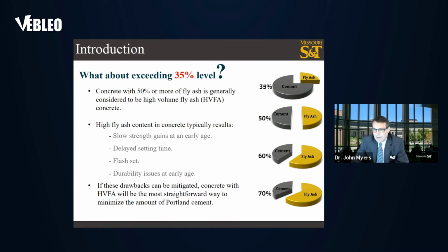So high volume fly ash self-consolidating concrete, or HVFA-SCC, is proposed here as a sustainable concrete that merges attributes between high volume fly ash concrete properties and self-consolidating concrete. And as I mentioned in the previous slide, currently ACI limits to 35%. So our question is, can we start to greatly increase the amount of fly ash, 50, 60, and even 70%, thereby reducing the impact of CO2 emissions in terms of the use of Portland cement?